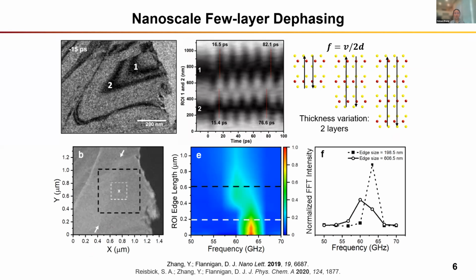And further, we can really see the significant effect of the probe size in resolving the frequency difference due to the 2 layers. So this panel in the middle plots the average oscillation frequency as a function of the size of the ROI. So initially, the ROI, which is labeled in white, only contains a uniform thickness. So there's a single frequency at 63.3 gigahertz.